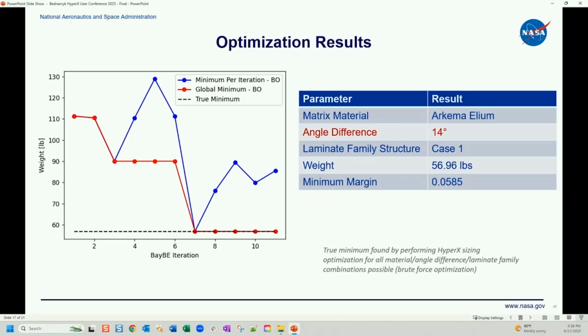How do we know it's the optimum? That's what the dashed line is. We essentially took everything the same and ran every permutation of those cases to make sure it had found it. Actually, we didn't know if it had worked or not, but you can see it did. We confirmed, looking at all the data, it did find the actual optimum from all the permutations it had access to.